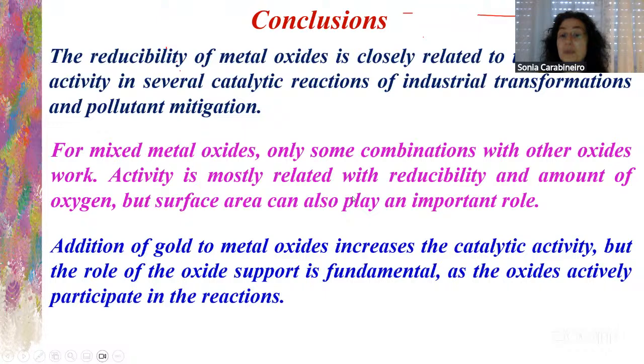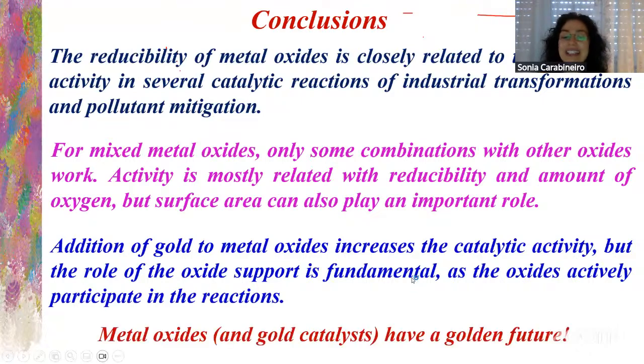Addition of gold to metal oxides, we saw that it increases the catalytic activity, but the role of the support, especially its reducibility, is fundamental, as we saw. So the oxides actively participate in those reactions. So we can say that metal oxides and gold catalysts have a golden future.